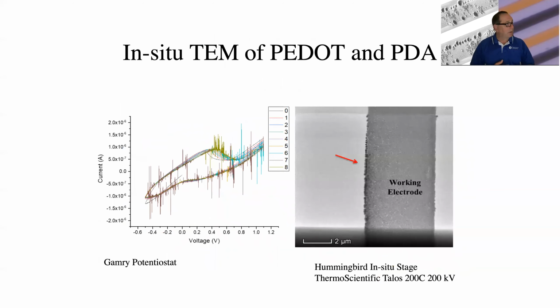I'll just conclude by saying we're also continuing to do a bunch of TEM. So my lab is currently actively exploring the use of liquid cell TEM, especially using an electrochemical cell. We can do the polymerization in the transmission electron microscope. And here's an example of PEDOT, and in this case, polydopamine, growing on an electrode. This happens to be a Hummingbird holder that we are putting into our 200 kV Talos.